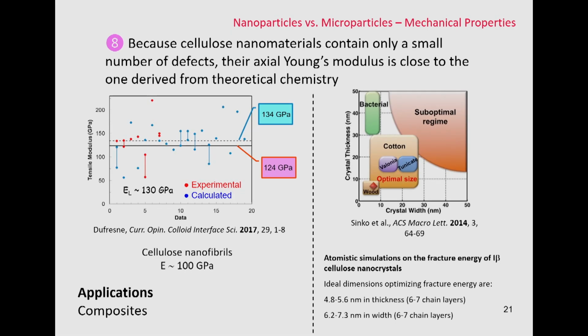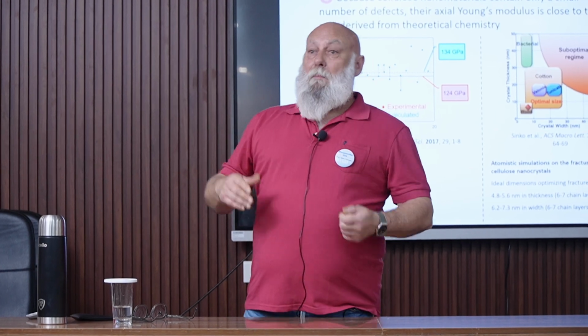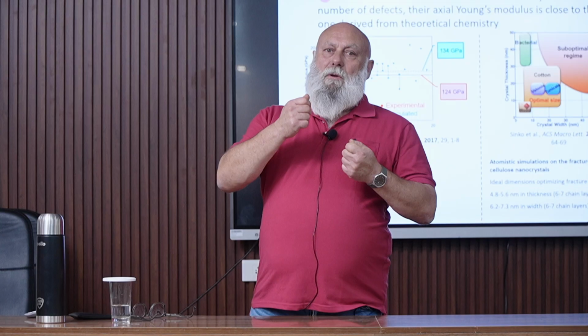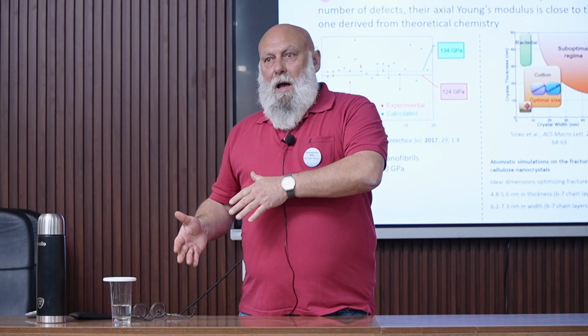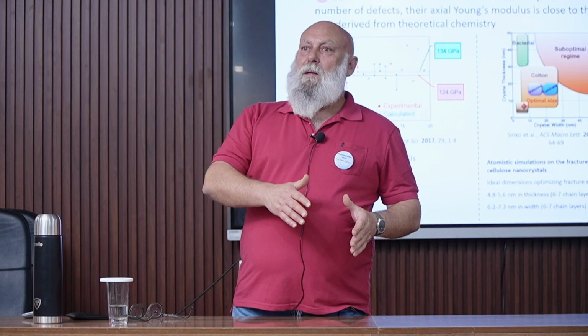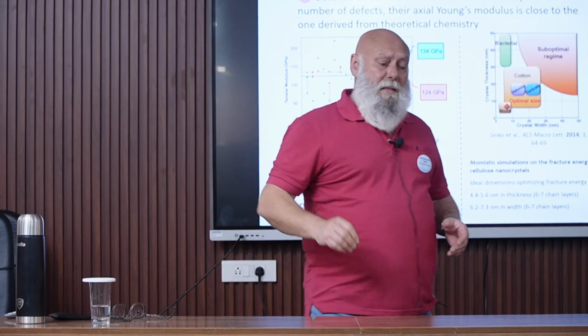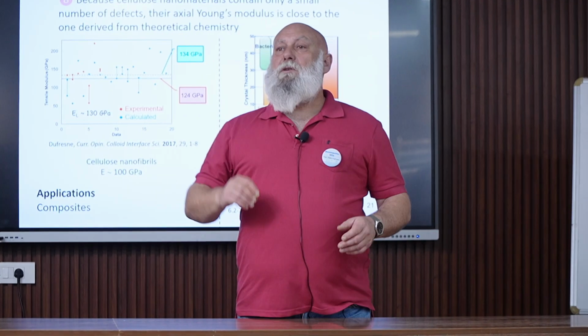Okay, what exactly can we get from this testing? Actually, I didn't get the modulus. For getting the modulus, we are using this one. In this work, they determine the modulus of just the crystalline part of cellulose. This is difficult to determine because the crystalline part is embedded in amorphous domains. When you perform a tensile test on a fiber, first it is difficult to perform it on a single fiber, but if you can do it, you have the modulus of both the amorphous and the crystalline domains. The interest in what they perform is that they record an X-ray diffraction pattern during the tensile test.